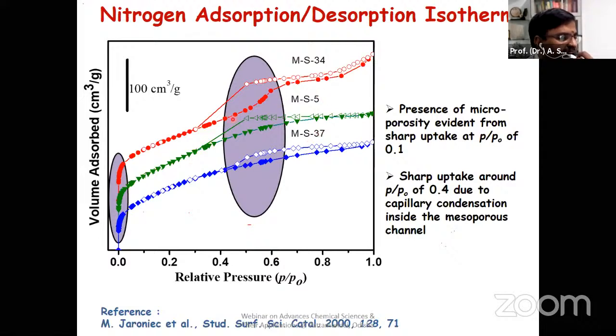Then there is multilayer adsorption. You can see continuous nitrogen uptake in the relative pressure range of 0.4 to 0.6. That indicates that the pore sizes are quite broad. Continuous molecules are adsorbed, and then there is pore filling, that is capillary filling. You can see that capillary action. That's why it's called capillary filling of the molecules, and it forms the meso-micro composite material.